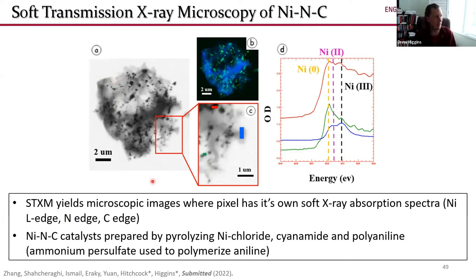So what we can do is we can take a STXM image, we can integrate the XAS spectra collected in the different regions, and that can give us insight into what types of structures are present in these materials and where they are present. So as an entry point to using this technique to understand these catalysts, we prepared some of them by just mixing together nickel chloride, cyanamide, polyaniline, and ammonium persulfate to make some materials that we could hopefully allow us to understand these materials with spatially resolved information.